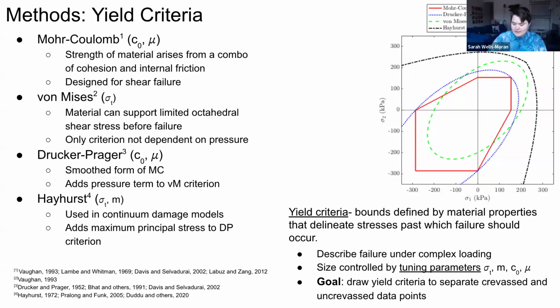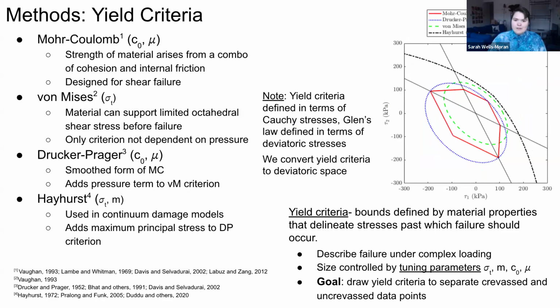And a last point is in David Vaughan's paper, he plotted everything in Cauchy stress space. The challenge with yield criteria is that they are all defined in terms of Cauchy stresses, but the way that we infer stresses from velocity data, all of the stresses come out in terms of deviatoric stresses, and so you can't just plop one on top of the other. So instead of converting the inferred stresses into Cauchy stress space, we converted the yield criteria into deviatoric stress space. And so they look like this in deviatoric stress space. If you're familiar with yield criteria at all, they might look a little bit different. It's that conversion that causes the different shape.